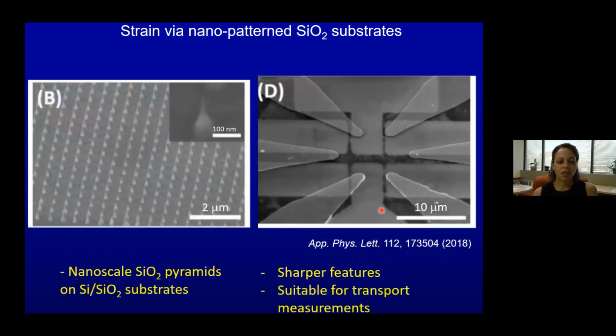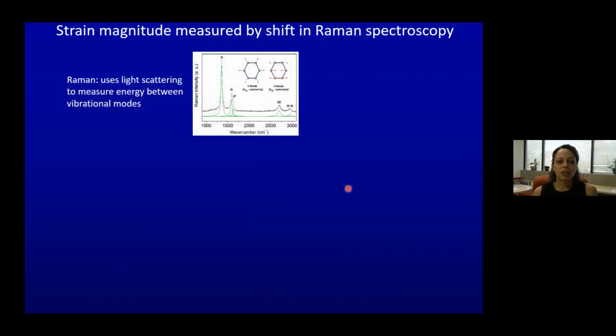Okay, and this was really nice for us because you can see the scale of each of these pyramids. This scale bar is 100 nanometers, and so the tip size here is less than 20 nanometers. So we have very sharp tips and nanoscale pyramids on silicon oxide substrates, sharp features, for transport measurements. Okay, so you can actually see here the pillars. The dark gray is the graphene, and then these things coming in are our contacts where we make electrical contact to it.